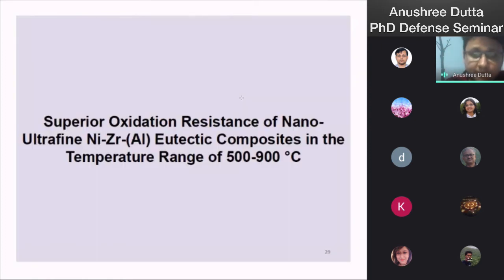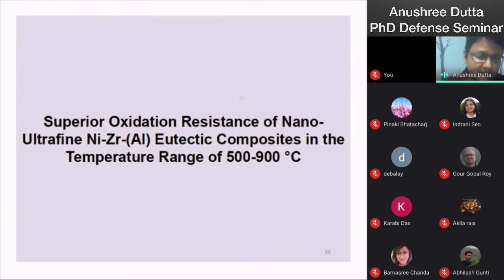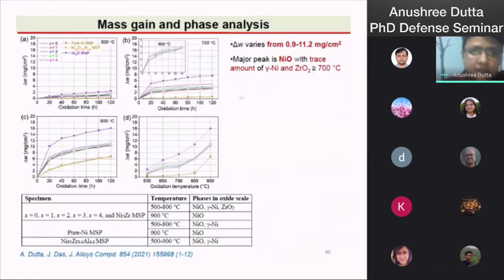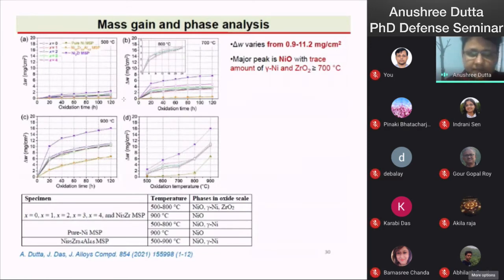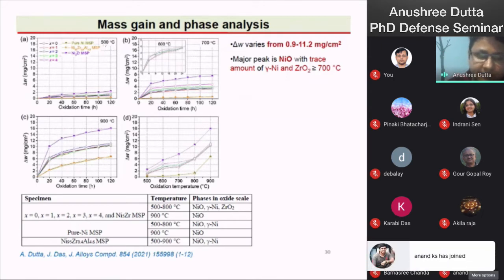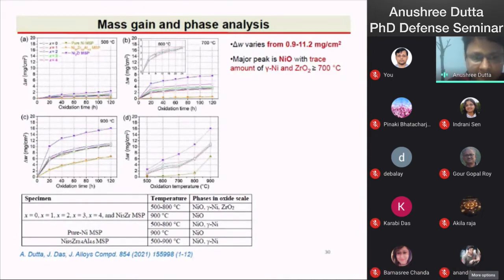My final chapter is superior oxidation resistance of nano ultrafine nickel zirconium eutectic composites in the temperature range 500 to 900 degrees centigrade. In this slide, the mass gain plot is given. All the NECs exhibited mass gain at 500 to 900 degrees centigrade. However, the mass gain increases with increase of temperature, and varies between 0.9 and 11.2 mg per centimeter square from 500 to 900 degrees centigrade.